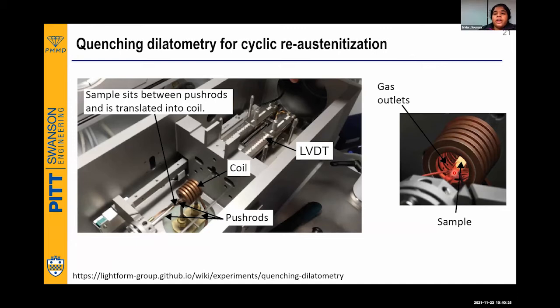And you have these gas outlets. Since we are going to cool it, in our case, we were using helium gas to cool because here, even argon is not sufficient. We need helium gas to achieve such high cooling rates. So we used helium for cooling at a cooling rate of 100 Kelvin per second.